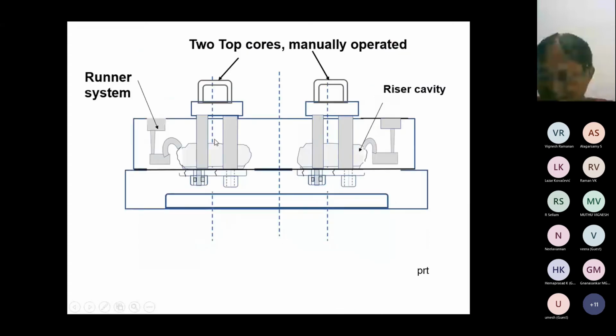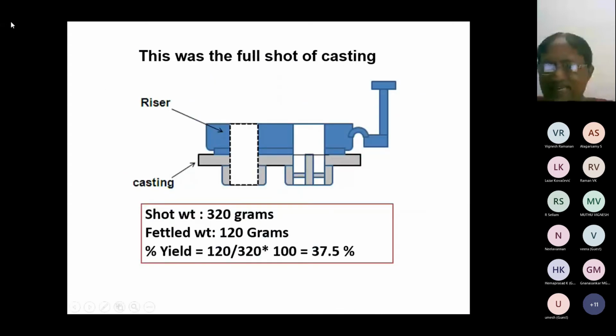From this die, we made a casting. This is the final shape of the casting that came out of the die. This is the casting, with such a big riser and all that. Shot weight was 320 grams and fettled with only 120 grams. Percentage yield is only 37%. Very, very low. On top of it, very difficult to hold this casting. We had a lot of accidents also. One of the people cut his hands also. Very, very difficult to fettle the casting. So fettling also has to be considered when you make a die.